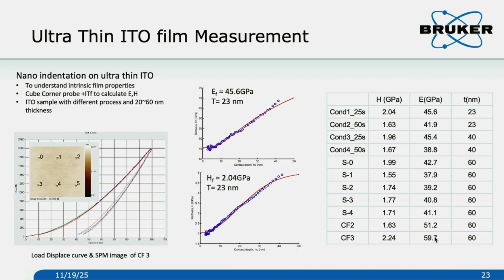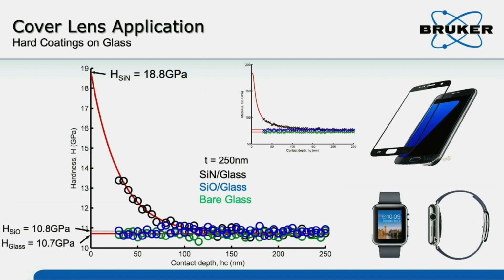So you see the substrate effect starts very, very early, around 5 nanometer, right? Almost 5 nanometer. This is hardness, modulus. So this can just help us to understand, if you don't have the continuous measurement, you are not going to get the result. Probably you select the wrong data here, you get the modulus in a different range. So this is very important.